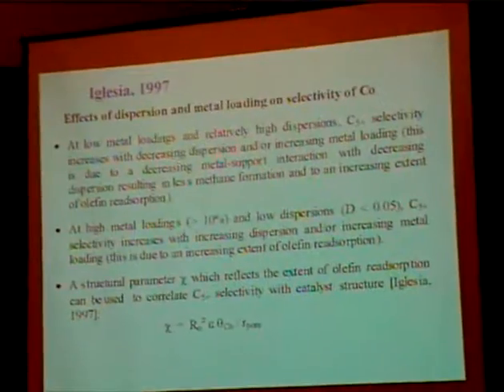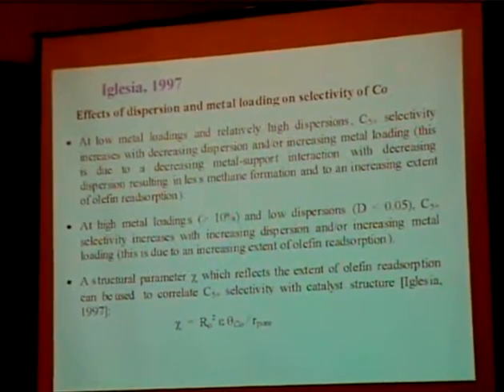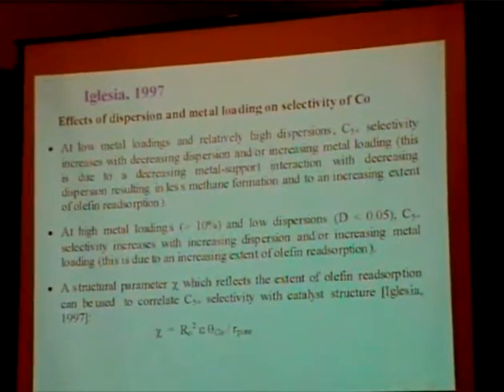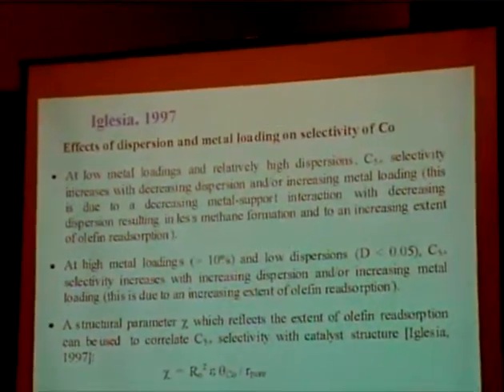If you start at low metal loadings and relatively high dispersion, the C5 plus selectivity is found to increase with decreasing dispersion and increasing metal loading. That's due to the elimination of metal support interactions.